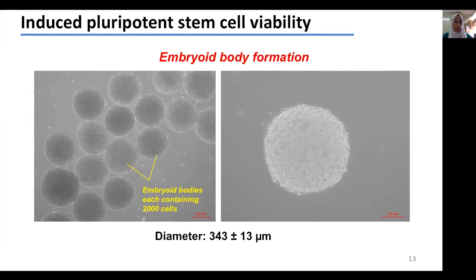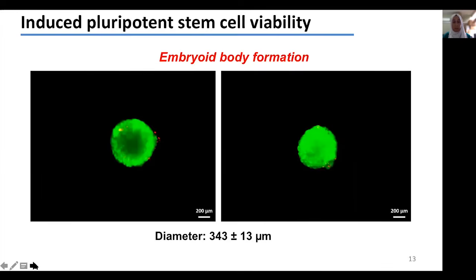These embryoid bodies were then seeded onto the nanofiber scaffold, and after 24 hours, we performed live and dead staining on the cells to see whether the cells were still viable or not. And these are the results that were obtained after the live and dead staining. So basically, all the live cells are stained in green and the dead cells are stained in red. Therefore, we can conclude that most of the cells were viable on the scaffolds, and there were very few dead cells on the seaweed-derived polysaccharide-based scaffolds.